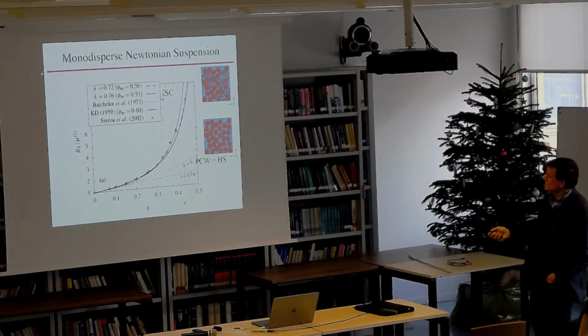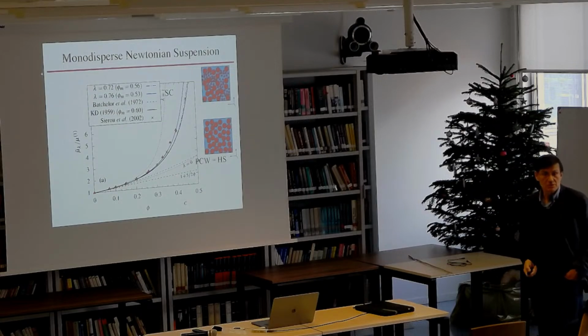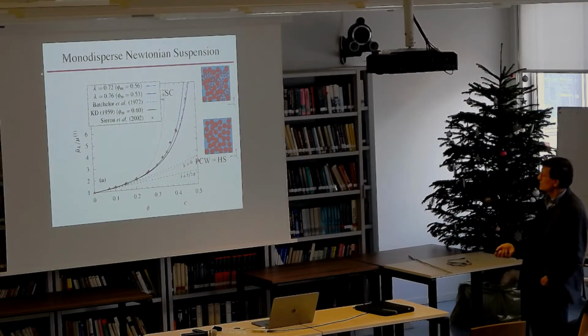If you put the self-consistent estimate, lambda equals 1, you get something that's just too stiff or too viscous. And if you put in lambda equals 0.72, you get this black line here.